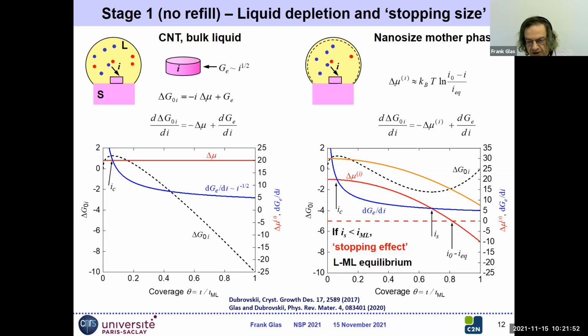There are two things to notice. First, that this stable equilibrium occurs at a coverage or number of atoms in the island, which is less than the one which would ensure equilibrium between the liquid and the bulk solid, which would be here. That is less. So actually, we have an equilibrium between the liquid, depleted liquid, and the edge of the monolayer, not between the depleted liquid and the bulk crystal.